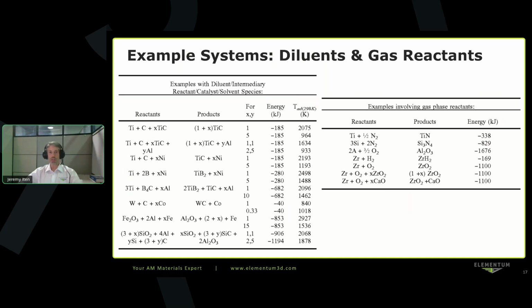You can also do gas phase reactants by controlling your process gas, for example, using nitrogen instead of argon, adding in controlled amounts of oxygen, things like that. And you can therefore form oxides, nitrides, hydrides, or other product phases using gas as well as solid phase. Mostly what we're doing is primarily solid type reactions. However, we have looked at gas phase reactions as well.